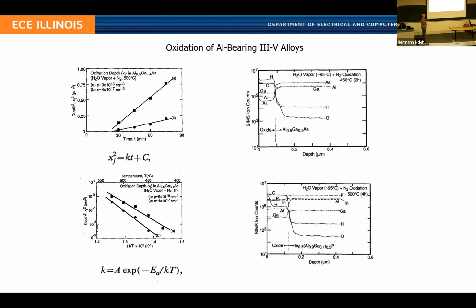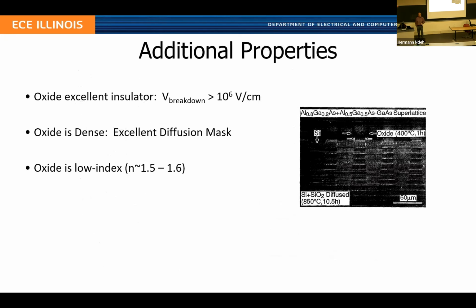What we did characterize is that the oxides were robust, and we really didn't see additional oxygen or hydrogen from the process migrate into the semiconductor film itself. This was true for both AlGaAs and the indium aluminum phosphide oxide. Other properties we found are that it was an excellent insulator, with breakdown better than 10^6 volts per centimeter. It was an excellent diffusion mask, so you can see here oxide over a superlattice, and where you diffused in, it intermixed the superlattice. The oxide was able to mask the diffusion and intermixing in the superlattice, and it was low index, nominally 1.5 to 1.6.